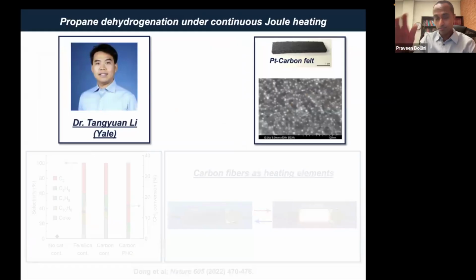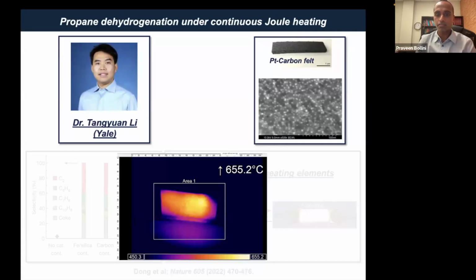Now, one of the things that I'm just trying to emphasize here is that these reactors are a little bit more complex than initially envisioned. So in the interest of time, I'm going to maybe zoom through this a little bit faster than I otherwise would. So we have a platinum on carbon felt here, in which we're able to disperse platinum very uniformly on the carbon fiber, which would be heated, and then we're able to load these into a reactor.